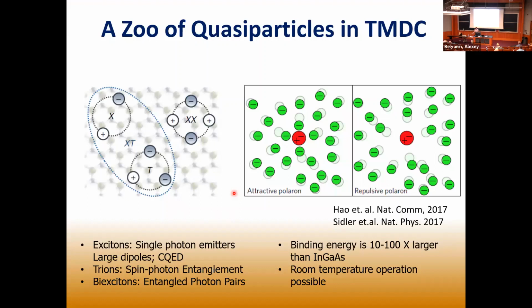So let me also expand on the quasi-particles that are relevant to optical property. I talked about the electron hole pair, which is an exciton. And because the material is so thin, the Coulomb field that binds the electron hole pair actually permeates outside the material, making the binding energy very strong, a few hundred meV. The typical band gap for a lot of materials we're familiar with is on the order of 1.5 eV. So a few hundred meV is very significant. And you can have an additional quasi-particle called a trion, which is an electron hole pair together with another electron, or 2 electron hole pairs bound together that we call a biexciton.